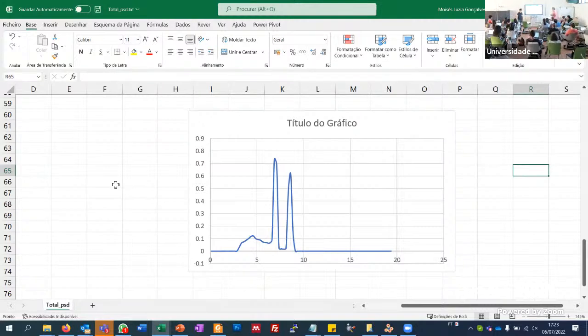Always keeping in mind a few things. One, in this case, I think in the model we were neglecting some things, including the hydrogen atoms were not there. Okay, we have to add them to the XYZ file, they were not there. Another point is that the CIF file is for something that is 100% crystalline, and in the experimental sample, sometimes there are some defects, and this is very frequent in some kinds of families of materials. Metal organic frameworks suffer a lot of defects, big portions of the linkers that are not there, and pores are much larger than they should be.